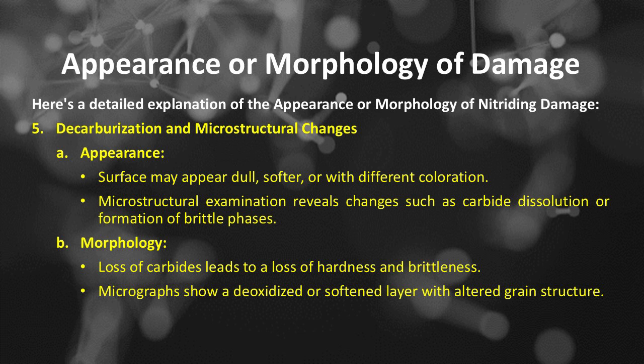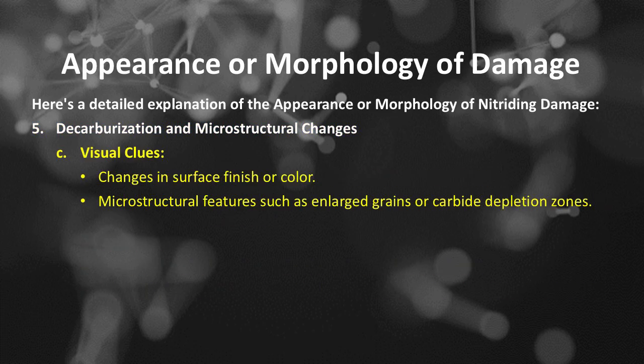Morphology of decarburization and microstructural changes: loss of carbides leads to a loss of hardness and brittleness. Micrographs show a decarburized or softened layer with altered grain structure. Visual clues: changes in surface finish or color, and microstructural features such as enlarged grains or carbide depletion zones.